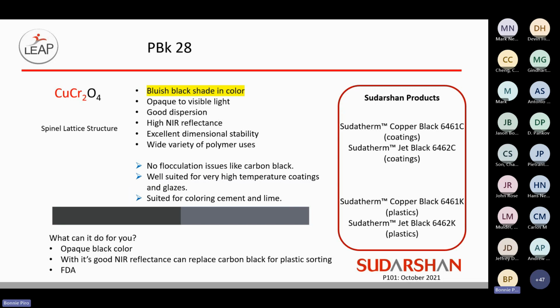The Pigment Black 28 is in the spinel category as well. It's a bluish black in shade and color, opaque, of course. And although I don't like to compare it to carbon black, I will in a couple of scenarios. It doesn't flocculate like a carbon black would in liquid coatings. Certainly well suited for high temperature coatings and glazes and coloring cement.